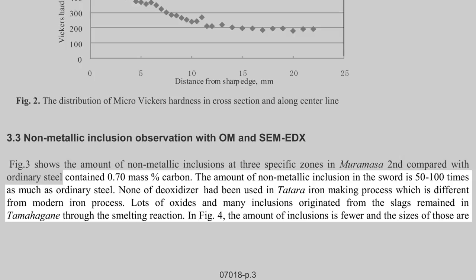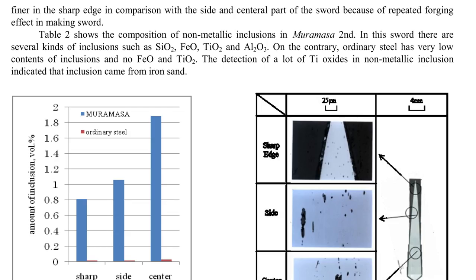Lots of oxides and many inclusions originated from the slags remained in the tamahagane through the smelting reaction. The amount of inclusions is fewer and the size of those are finer in the sharp edge in comparison with the side and central part of the sword because of repeated forging effect in making the sword.